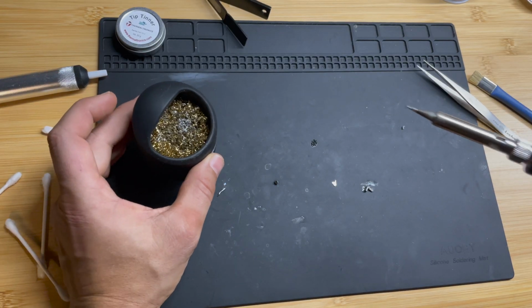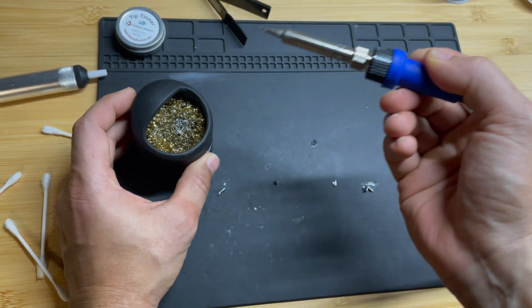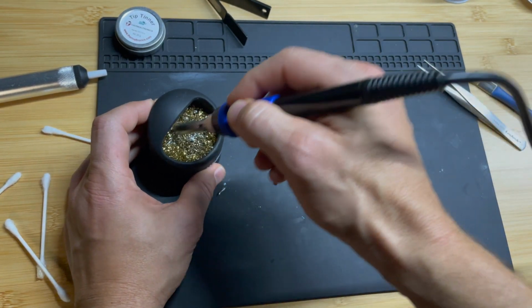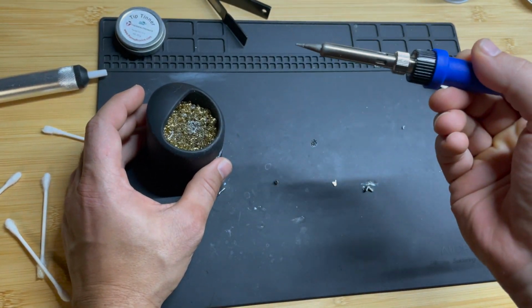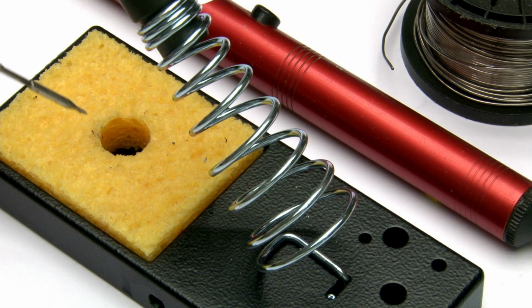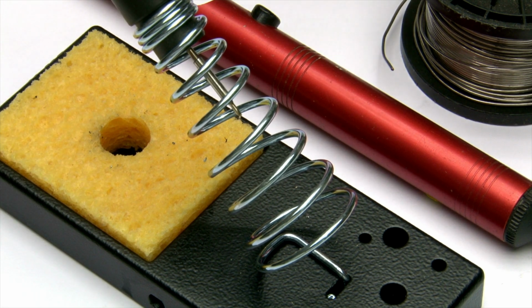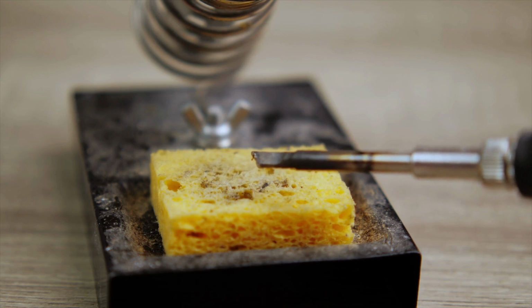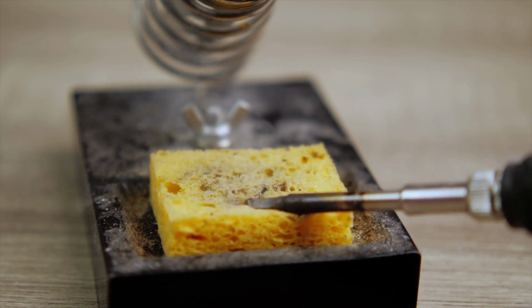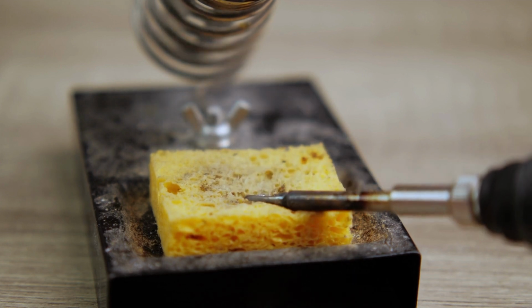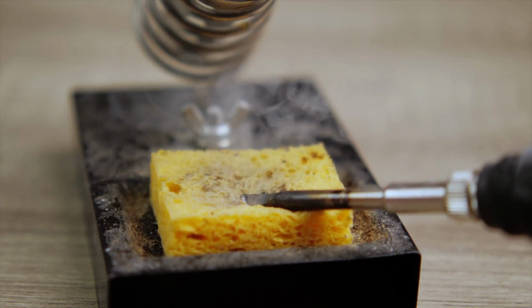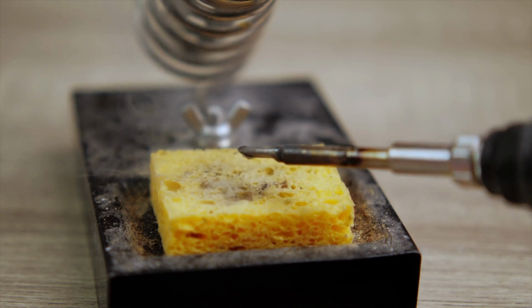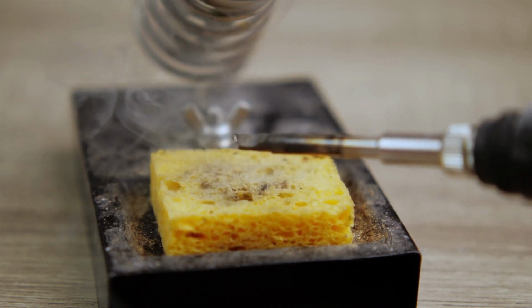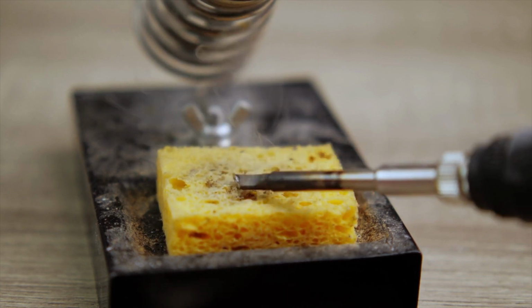This is a brass wire soldering tip cleaner. And if you don't have one of those, you need to get one of these right away. These things are going to help keep your tip clean and remove oxidation. You can also use one of these yellow cleaning sponges to clean your soldering off, but most people don't actually use these things correctly. You're really just supposed to quickly, lightly touch this thing once or twice to shock oxides off of it. When you drag the soldering iron or tap the soldering iron repeatedly onto the pad, you're going to lose a lot of heat. And when that happens, the soldering station or pen is going to try to heat up really quickly. And most of the time it's going to overshoot the set point, which isn't ideal because now you're increasing the temperature above what you're trying to have it set at.